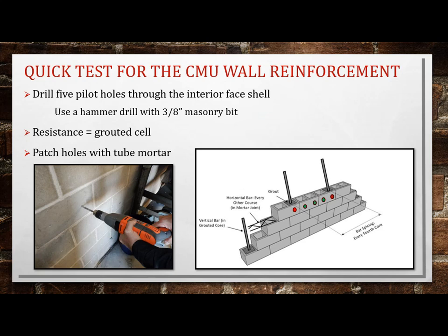So anyway, you drill your first hole, and then you drill 5 successive holes. If you get to 5 cells, and every one of them is empty, if you're drilling and it just punches in, it's empty. If you do 5 of them in a row, chances are it's not grouted. You should probably then go to your door frames or your window sills and see if they grouted those. Those should be grouted and reinforced. But that's not to say hollow walls don't have some advantages. They're not as strong, but they have better sound resistance, and better thermal properties. They don't conduct heat as much.